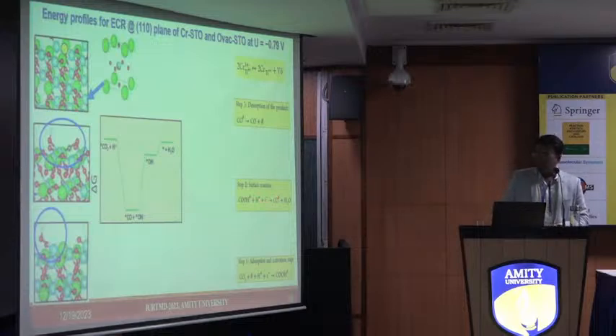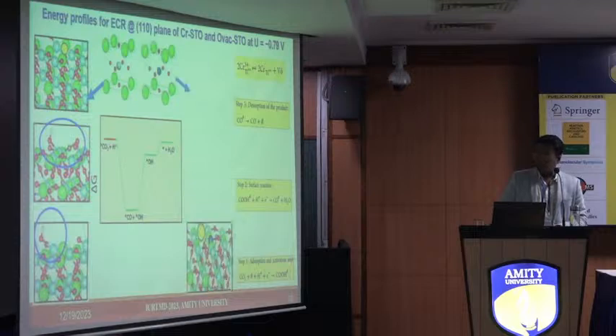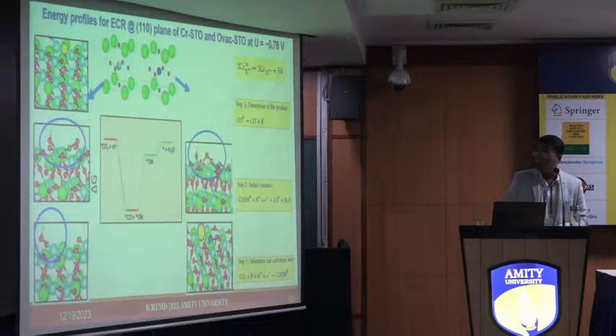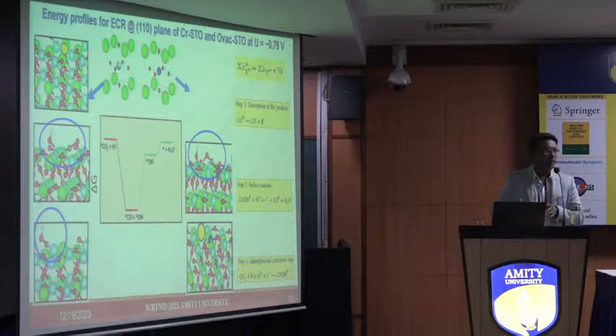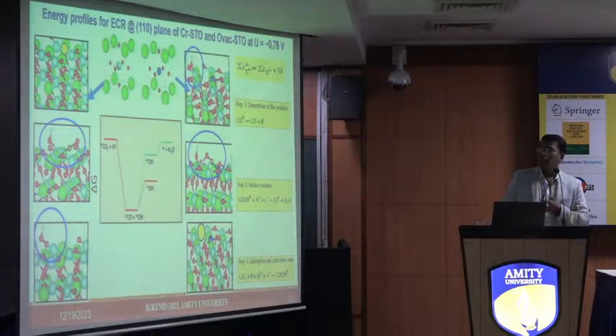Now, this was for the strontium titanate. If I compare, the red points over there are for the chromium doped strontium titanate. What you can notice is that the first step is almost similar because the number of oxygen vacancies is not altered that much. There was a little increase in the oxygen vacancies. Importantly and interestingly, what we found is that this step, the desorption of the OH molecule, is now much more favorable as compared to the undoped sample.